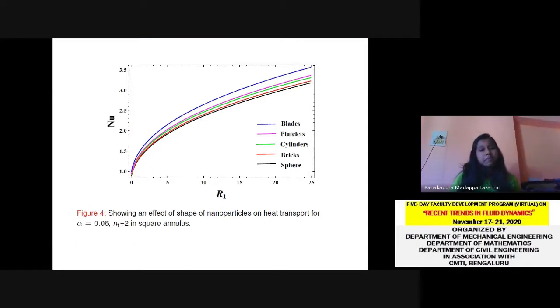So the thermal conductivity inequality is given here. The thermal conductivity of a blade-shaped nanoparticle is highest compared to platelets, cylinder, bricks, and spherical. And the same pattern we can observe for the Nusselt number. As we know, the thermal conductivity is the key factor for the heat transport in the system. Definitely the heat transport in the system, that is the Nusselt number, follows the pattern of thermal conductivity. So the heat transport in the case of blade-shaped nanoparticles is maximum, and the spherical shape is minimum.